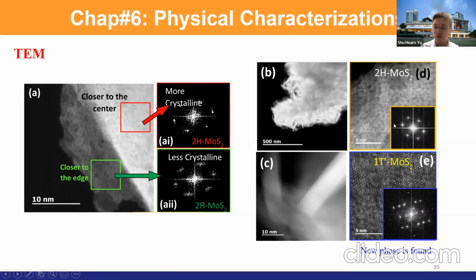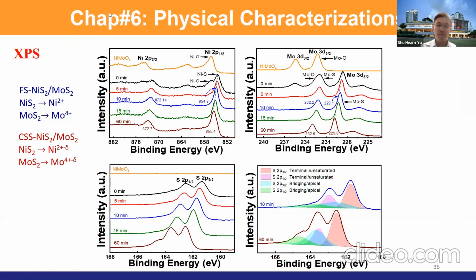And then if you perform controlled surface sulfurization, in addition to those two compounds, you have one more compound form, 1T prime MoS2. So this compound can only form at the intermediate phase. At high temperature, this compound will be converted to 2H-MoS2. And these materials are very conductive, and also very active for the HER reaction. So this is a very important slide.